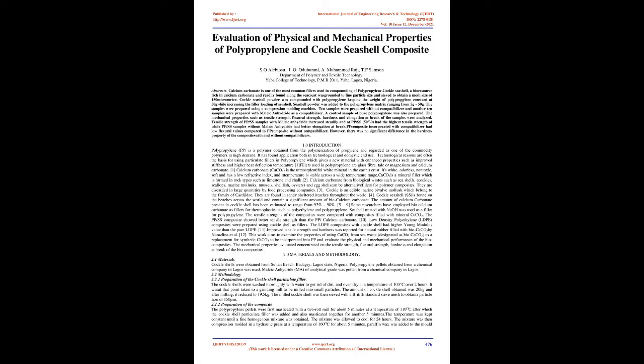sieved to obtain a mesh size of 150 micrometers. Cockle seashell powder was compounded with polypropylene, keeping the weight of polypropylene constant at 50 g while increasing the filler loading of seashell. Seashell powder was added to the polypropylene matrix ranging from 5 g to 50 g. The samples were prepared using a compression molding machine.